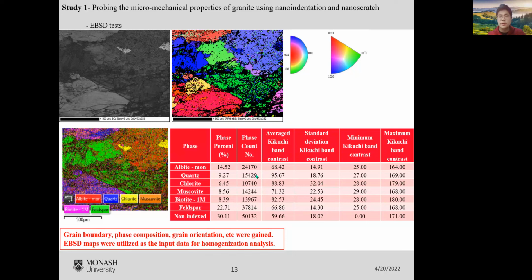In addition, the EBSD test has been performed in order to obtain the grain boundary and grain orientation, and these EBSD maps have been utilized as the input data for the homogenization analysis.